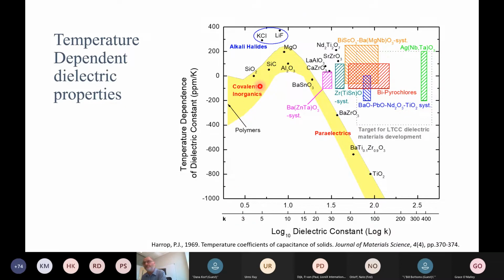They're covalent. They have different polarization mechanisms that respond in a way that we see a negative temperature coefficient of dielectric constant. And as we have more ionic character of the material, a lot of oxides, we can then see that that temperature coefficient fundamentally changes from negative to positive. And then as we increase permittivity to very high values, we end up in these sort of paraelectric materials. It's sort of the high temperature range as they go from a paraelectric to a ferroelectric phase transition.